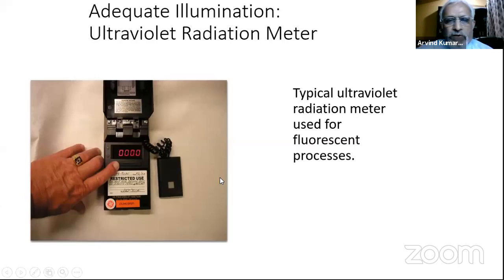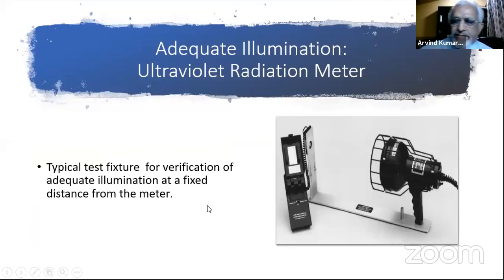Now for fluorescent method, you need to have a UV light and the black light meter, which will measure the quantity of the lighting which is there, the UV light intensity. When you're doing a fluorescent test, it is also important to see that apart from 1000 microwatts per centimeter square UV light intensity, you make sure that there is no leakage of white light from any of the darkened area that you have made for doing fluorescent MPI or fluorescent PT. So the leakage up to 20 lux is permitted as per the code. If the leakage of white light, that is normal light, is more, then you have to prevent and take care of that leakage light.